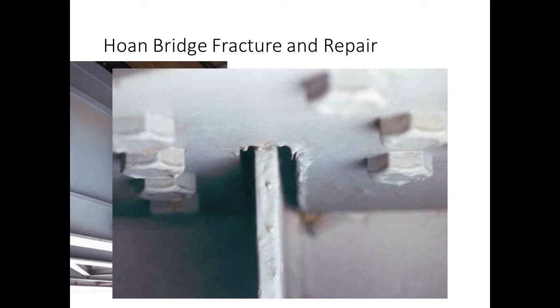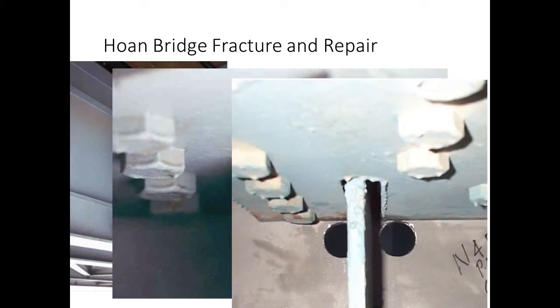Well, the investigators concluded that these welds created a condition of triaxial constraint and high stresses, so when they had a small pop-in crack, it became unstable and ran up and down the girders, causing the fractures. So Wisconsin DOT came in and did some rehabilitation by putting check holes below and above the shelf plate, so any cracks that occurred in this high stress area would be arrested before causing problems.